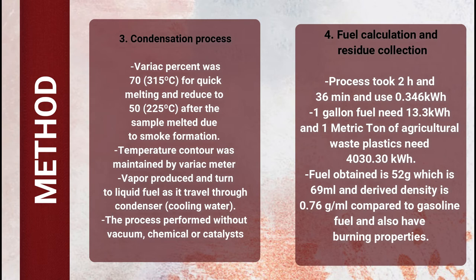The fuel obtained is 52 grams, which is 69 milliliters, and the derived density is 0.76 grams per milliliter, comparable to gasoline fuel. It also has similar burning properties.